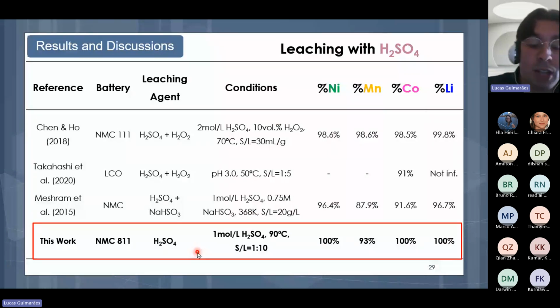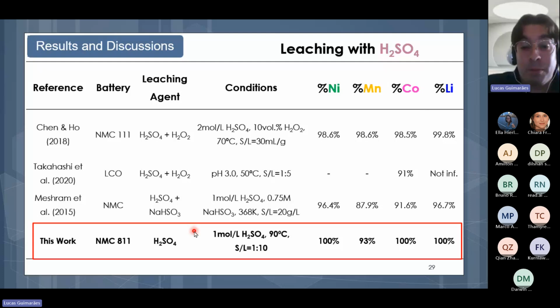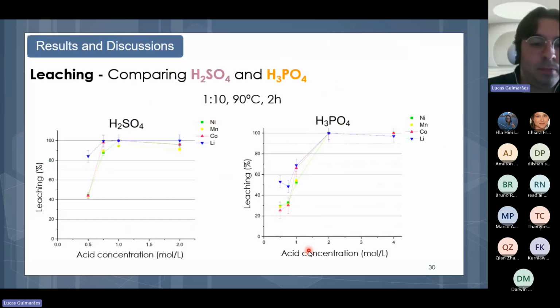And it's important here to mention that it's common to find in the literature the use and the injection of conventional reducing agents or optimizing agents in order to get more than 90% of leaching, reducing agents such as H2O2. And it's important to highlight that this work did not need to inject any other conventional optimizing agents, because the presence itself of metallic aluminum and copper in the black mass helped to get the results already of over 90% of leaching.